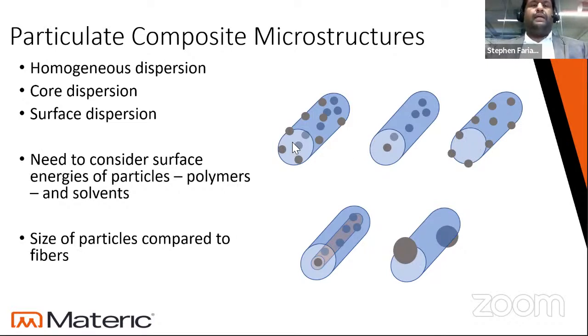And a lot of that will depend on the actual surface energies of your particle relative to your polymer that's solidifying as your Taylor cone is drying, as your fiber is drying, as well as their interaction with the solvent. And so if there's some kind of bias where the particles want to be interfaced with the solvent more than the carrier polymer does, then you might have this case where particles are actually speckling the outside of the fiber.